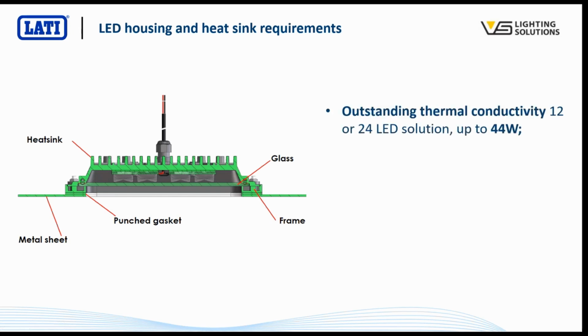So the key requirements of the heatsink part here, which is what we're focusing on, this heatsink part at the back: it must have outstanding thermal conductivity. This product is available in a few different configurations, but the highest power one of those is up to 44 watts. So that's quite a lot of heat being generated that we need to get away from the electronics if we want to maximize this lifetime.